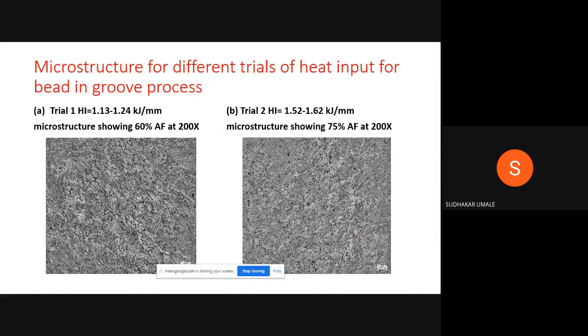These are the microstructures. I have selected heat input. I have taken three trials there. This is trial one. I have taken three currents, three voltages, and three welding speeds. During that period, my heat input is 1.13 up to 1.24 kilojoule per mm. And this is my volume fraction of AF, meaning acicular ferrite, at 200 times magnification of the microstructures.